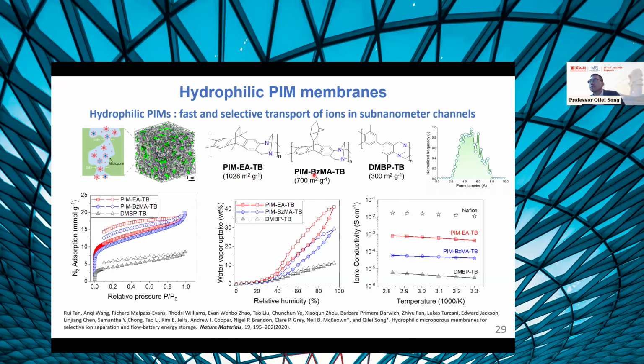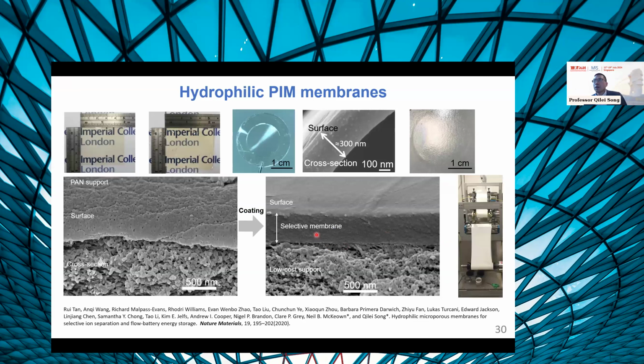We were able to tune this backbone structure to tune the surface area, and we can see that there's a really good correlation between the surface area and the ion conductivity. For PIM-EA-TB, you can see that they absorb relatively high amounts of water molecules, and the ion conductivity is relatively higher. This means that the water absorbed into these polymers can form interconnected water channels that facilitate the transport of small ions like sodium or potassium. And these polymers are solution processable, so we were able to cast, spin coat, or blade coat these polymers onto a support, for example, to get thin film composite membranes.